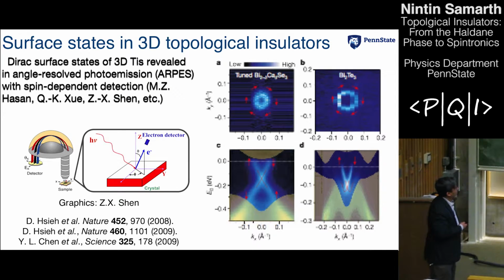They then carry out an experiment called photoemission, in which you bombard the sample with energetic photons, and then you look at the emitted electrons, and you measure the dispersion, energy versus momentum, and you can map out the band structure. And this band structure then shows you the existence of these topological, of these Dirac states.